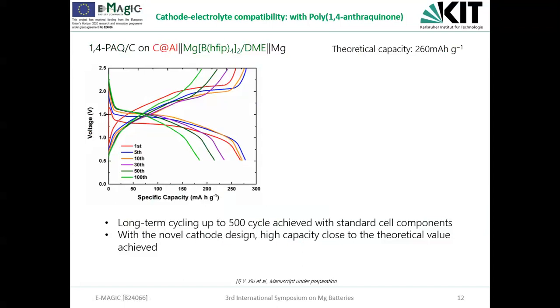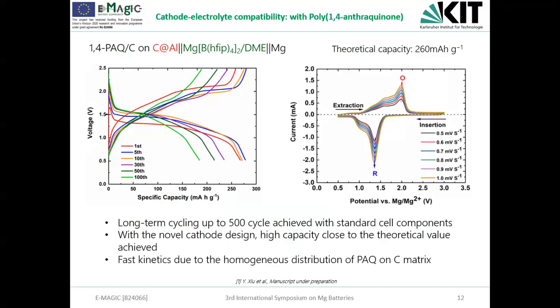Also, here we could achieve high capacity with the new cathode formulation, and this is close to or even exceeds the theoretical capacity a bit. And with the homogeneous distribution of the active material on the conductive carbon, we could also achieve fast kinetics, as demonstrated here in the CV with different scan rates.